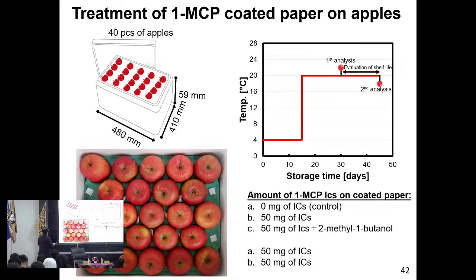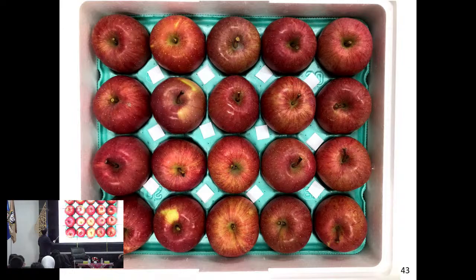So 40 pieces of apple in a polyester box were kept for 15 days, and then the temperature was changed to 20 degrees Celsius. Then first analysis, second analysis, and we check this is the Fuji apple.